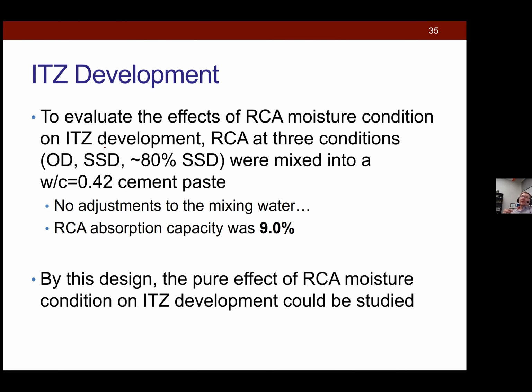So if you don't account for that when you're mixing your concrete, you can run into a lot of issues, right? If you don't measure the moisture content of your RCA and you don't account for this moisture difference and you mix your RCA dry into your concrete, guess what? That RCA is going to want to suck up all of the water that's supposed to be there for your cement hydration. That's going to cause a lot of issues. So that's what we were looking at in this study.